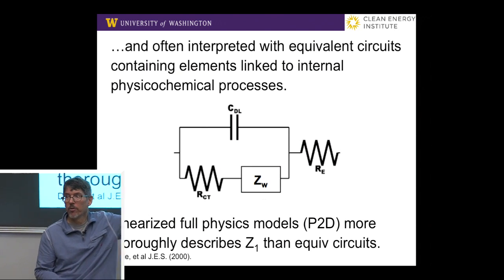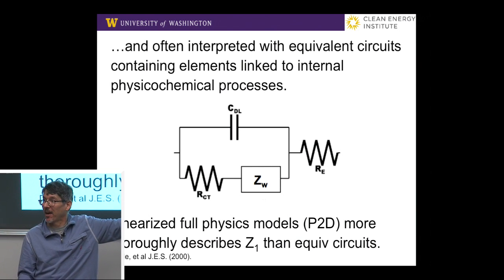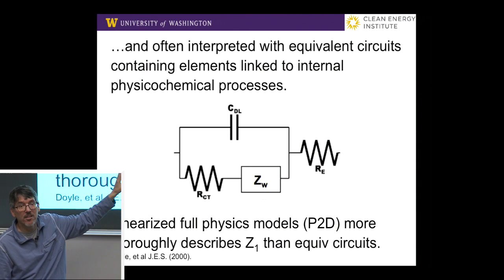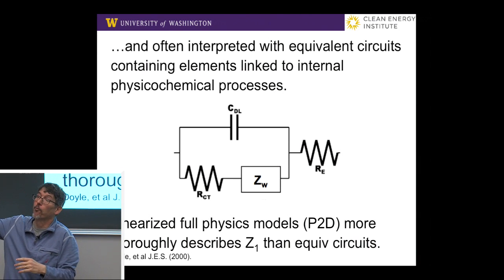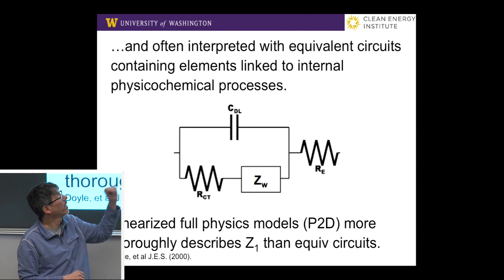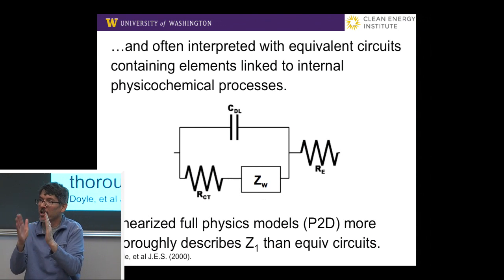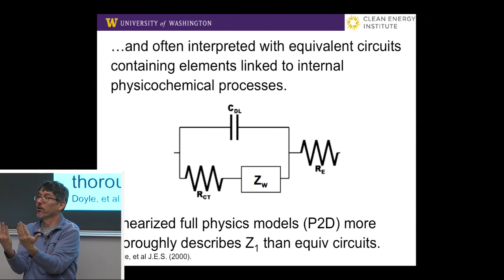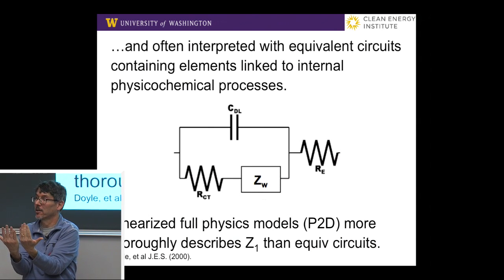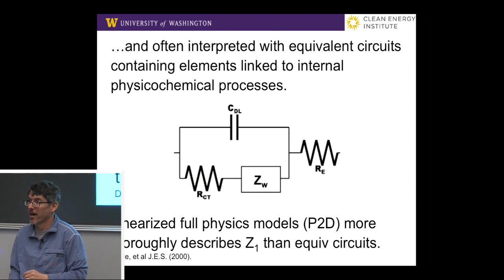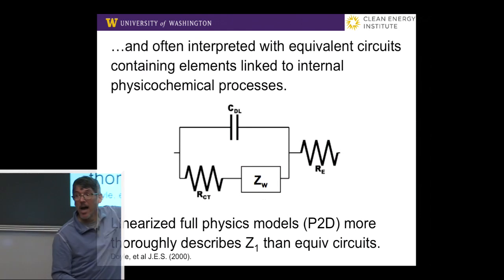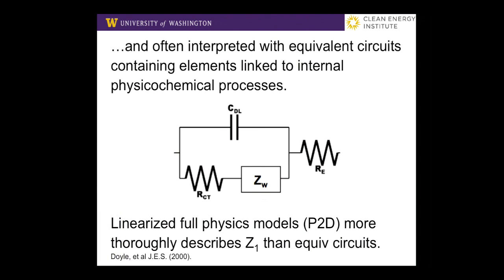I can show you the conductivity of the electrolyte, the geometric factors that go into the resistance of the electrolyte over there. And some electrodes, ZW is the Warburg impedance, that low frequency stuff is a transport-related impedance. Capacitance of the double layer, we've got the interface between an electronic conductor and an ionic conductor. That interface will have a capacitance that we represent by C double layer. And so each electrode will kind of look like this. But a lot of times you can only get these 1, 2, 3, 4 bits of information. But that's better than voltage, current, and time. We're now able to start poking at different physics that's going on the inside of that battery.